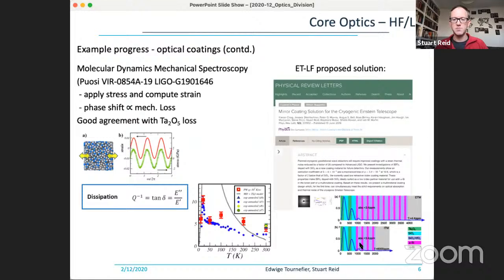And this is the paper again by Kieran Craig, which actually produces a possible coating solution for ET-LF, and that uses a mixed material coating design where we bury amorphous silicon containing multi-layer mirror coatings in the under layers where the electric field intensity is low. But in the upper layers, where we have a high amount of the laser light reflected, we switch to materials which have very high optical properties. And that allows us to mix materials which have good mechanical properties and good optical properties and appropriately position them in the coating so that we can exploit both the optical performance and the low mechanical losses.